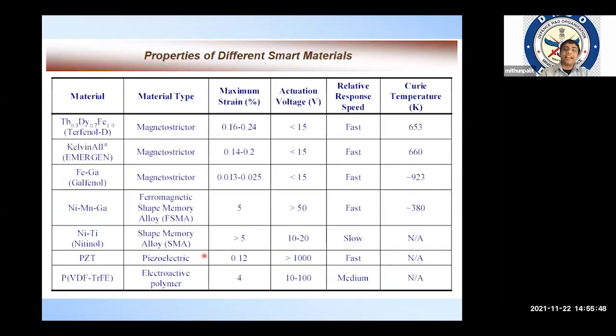So there are different types of magnetic smart materials. You can see that there are three magnetostrictive materials which show a strain of up to a maximum of 0.2%, and you need an actuation voltage of less than 15 volts. Whereas for the ferromagnetic shape memory alloy nickel manganese gallium, the maximum strain that can be realized in a single crystal is very high, up to 5%, but the actuation voltage required is very high, greater than 50 volts, which is a certain disadvantage in making a device for a mobile platform.